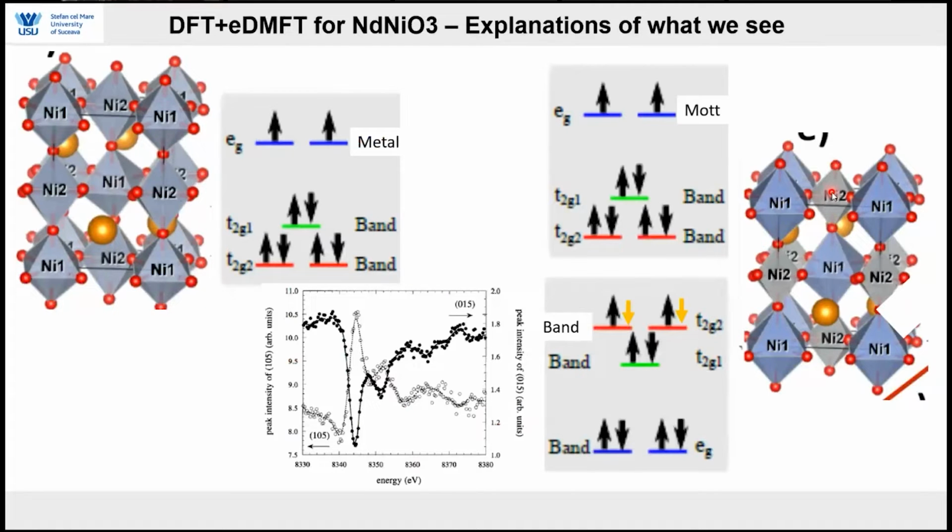Now, even further, since we see that for the contracted site, the orbitals all have a band-like character. What does it mean, band-like character? It means that the band is completely filled by 2 electrons. Now, if a band has 2 electrons, one spin up, one spin down, it means that this band cannot have a magnetic moment. Now, by looking at the electronic properties, we understood why one site has a magnetic moment and one doesn't have a magnetic moment in our calculation, which before we thought was a little bit puzzling.